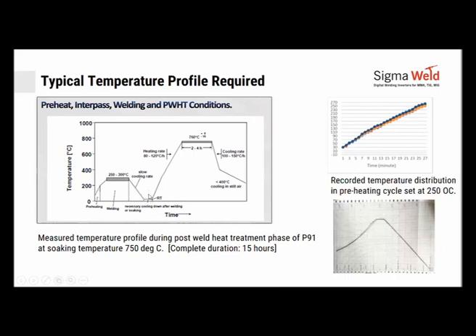Wait, complete your RT, and then you go in for a post heat cycle, which has a heating rate of 80 to 120 degrees per hour, depending on thickness. Then once you have achieved your 760 degrees, plus or minus 10 degrees is allowed. Hold it there for a period of 2 to 4 hours. We have done some trials where we have held it for as long as 8 hours and 10 hours to ensure proper normalizing and proper heat distribution all across the thickness.